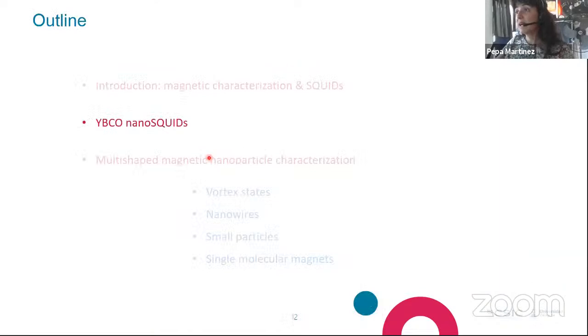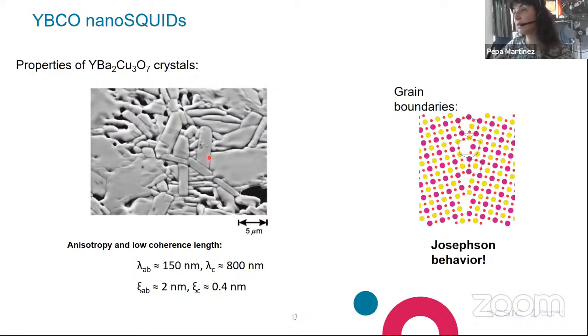Well, let me now just move to the main part of the presentation. This is where I will tell you a little bit about these YBCO nanoSQUIDs that we have been working with. YBCO is in principle a very nice material for the development of nanoSQUIDs because it's a high Tc superconductor. So it will allow ideally operation under large magnetic fields, and it is superconducting up to temperatures of 80-90 degrees.